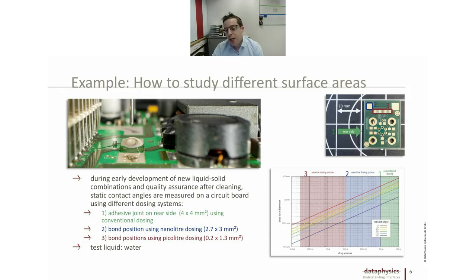So as a little example, we take this PCB board. And we have different locations on this PCB board where we want to judge how good the wettability is. Was it cleaned well? Was it coated well? So we want to do this on the rear side of the substrate here. There we have a relatively big area available, 4 millimeters by 4 millimeters. We want to do it here in area number 2 in this bonding position. There we have only around 2.7 by 3 millimeters available. And then we also want to do the same analysis here in this region where we only have these tiny pin surfaces available. They are only 200 micron wide and 1.3 millimeter in length.